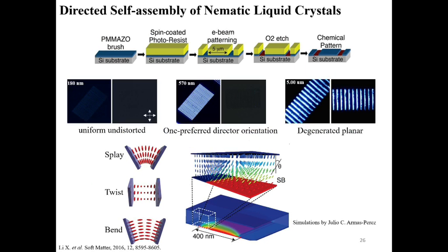We then tested a substrate modified with such a layer and opened trenches on it, and we found that by varying the width of the trench, we can control the liquid crystal to all align along the trench direction within a certain width range. Otherwise, if below this range, it will be uniform homeotropic, a uniform stand-up alignment.